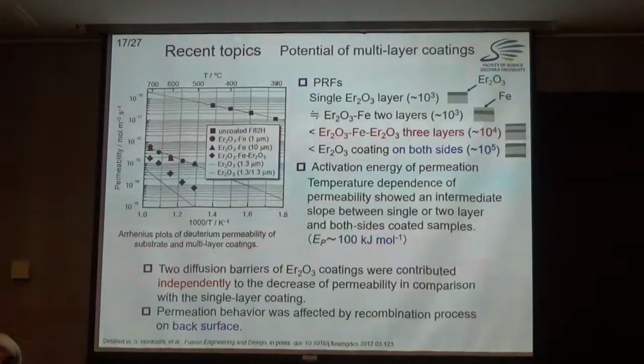Then when we coat Er2O3 again, so this is a three-layer coating, the permeation reduction factor increases to 10 to the power 4. In comparison, the both-side coated sample has a little bit lower permeation reduction. It means some dissolution or recombination process is important at the back surface. So the permeation behavior is affected by the recombination process on the back surface. That's one thing we found recently.